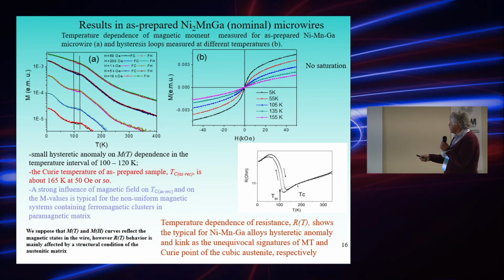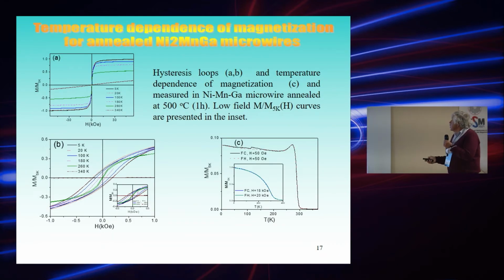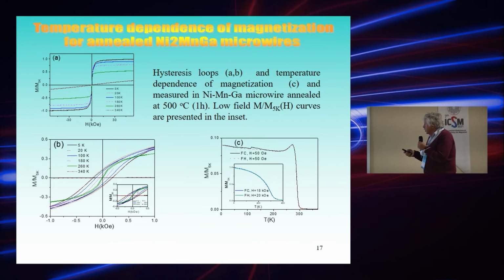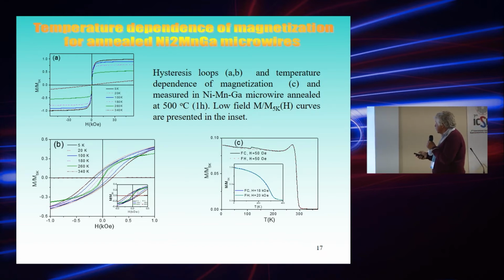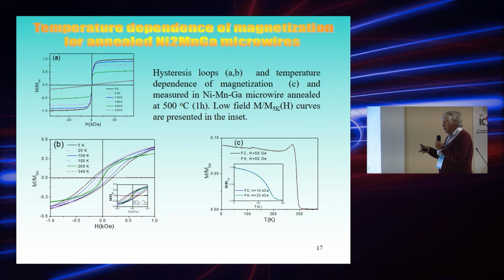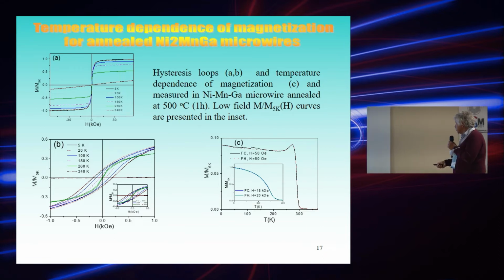The magnetization curves are responsible for the magnetic states, whereas the resistivity is more responsible for structural changes of our materials. One of the important features is that once we anneal our samples, we can release the internal stresses related to the fabrication technique. We did it, and now our materials present saturation even at higher temperature. They present a hysteresis loop with quite good typical ferromagnetic behavior, and a Curie temperature near room temperature, shown here.